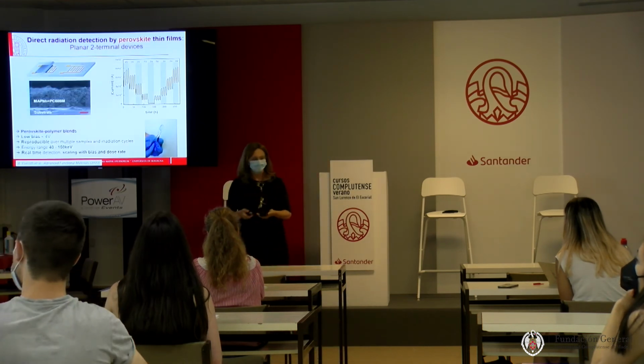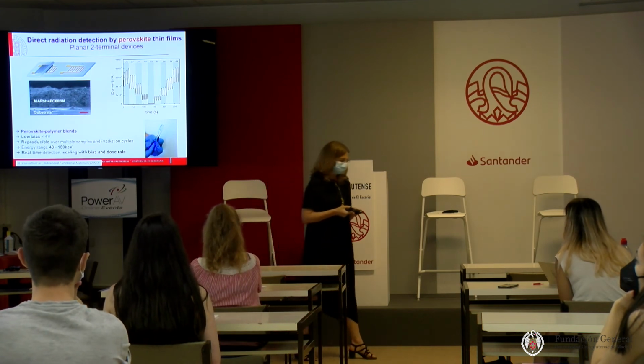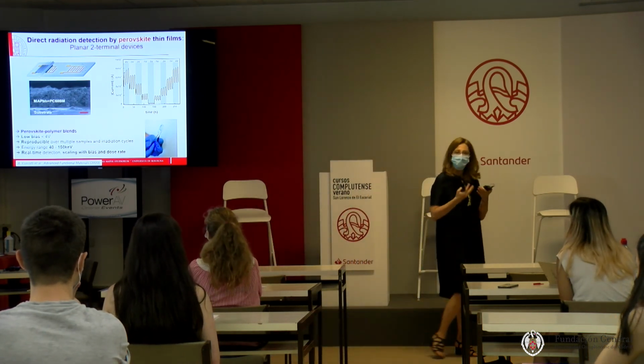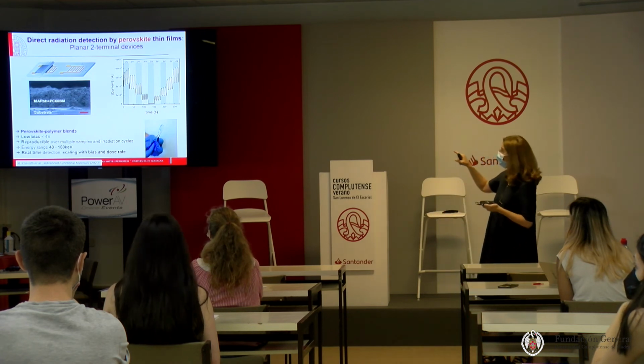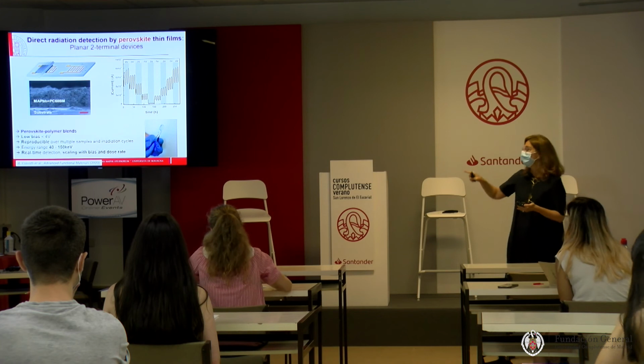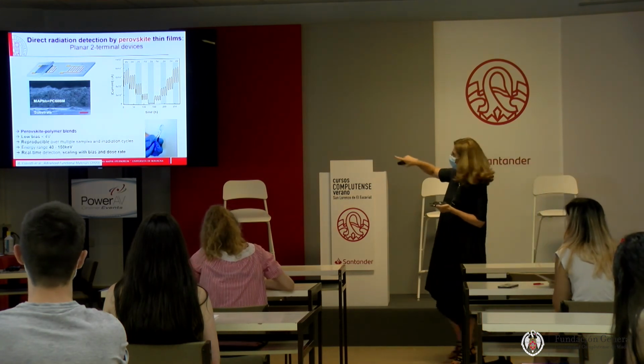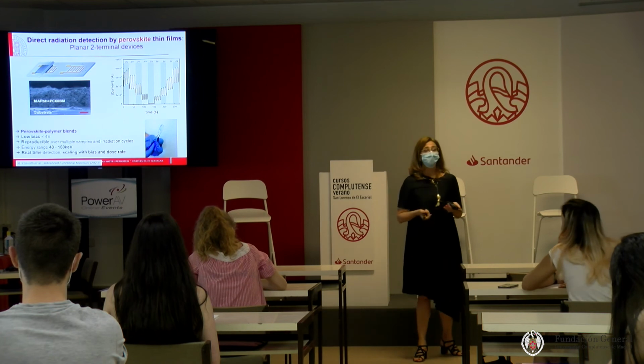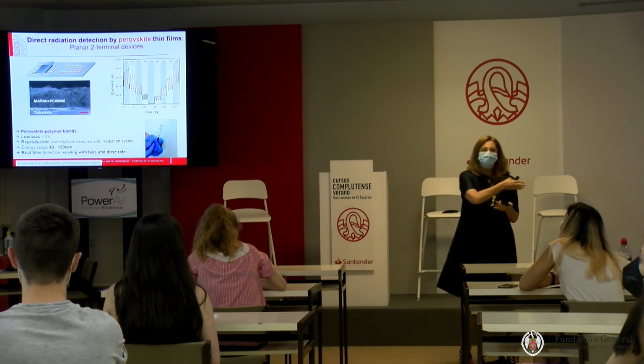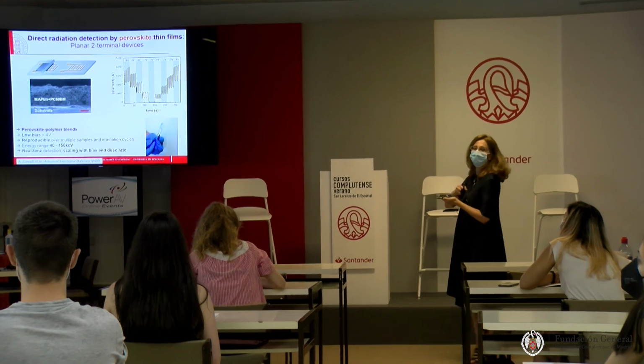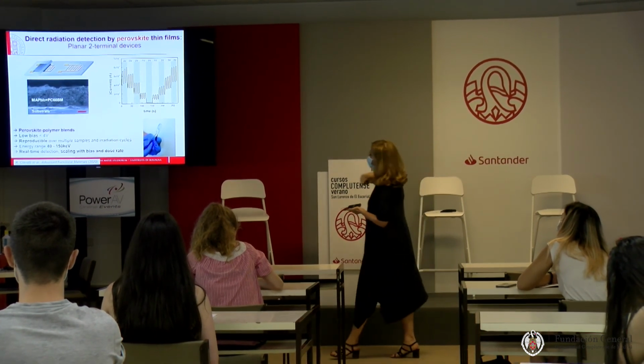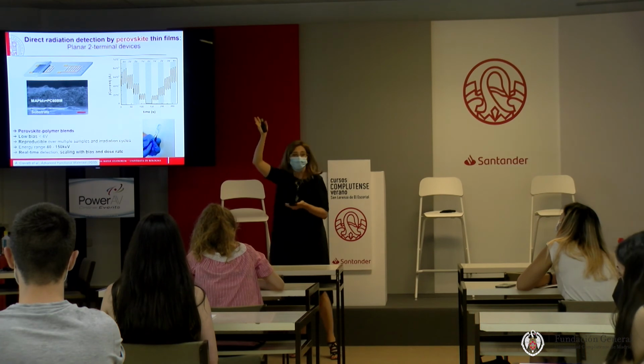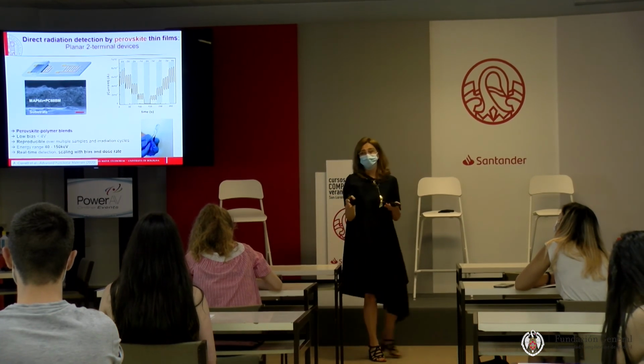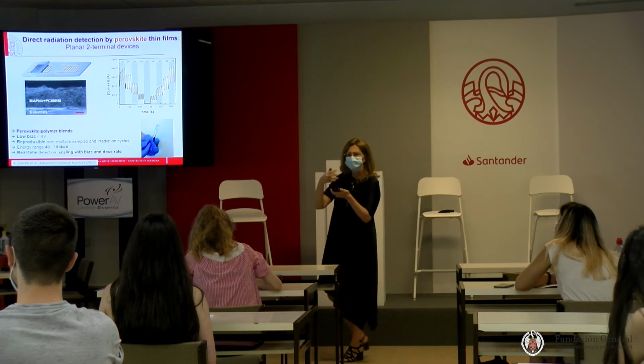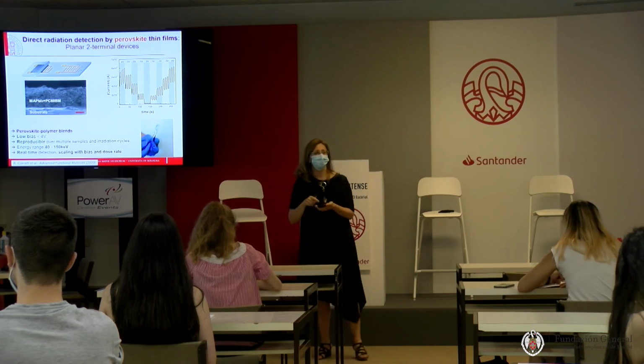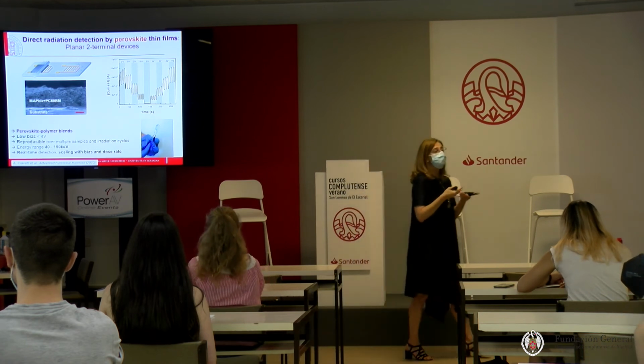Another suggestion for future material scientists is that you can combine and invent novel materials. Here what we're doing is combining perovskites, methylammonium lead iodide, with a polymer, with an organic material. We make a blend and we deposit our solution onto electrodes. So it's a very simple two-terminal device. This image you see is a cross-section in a scanning electron microscope that shows the very messy top layer and the substrate. Still, the material is messy, but it's not amorphous.